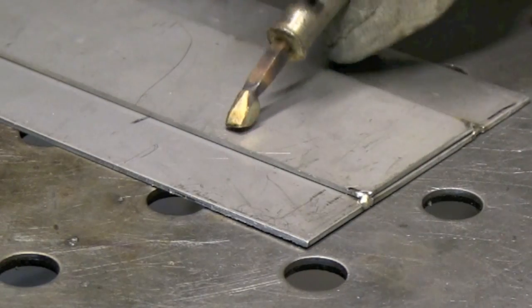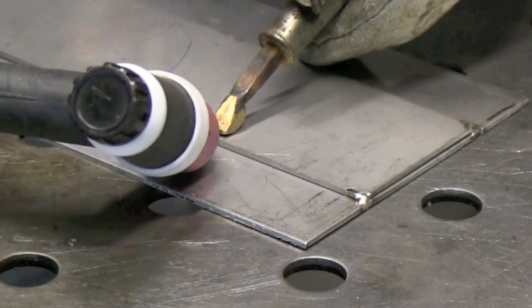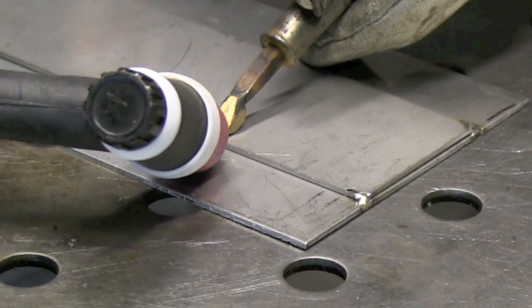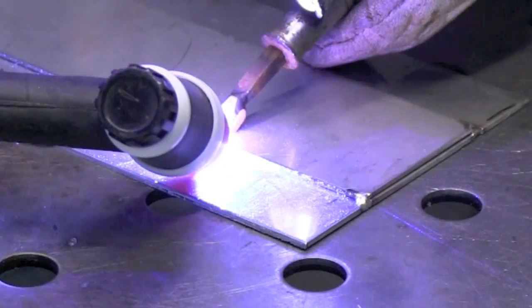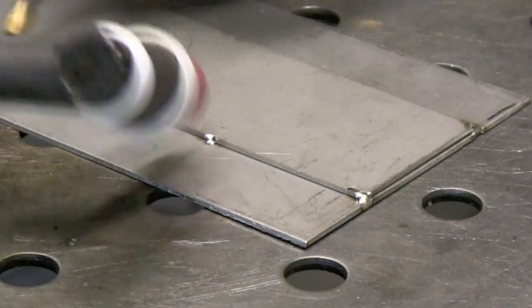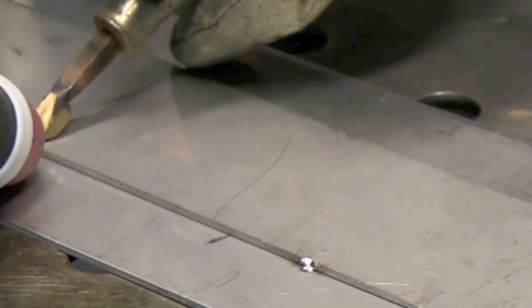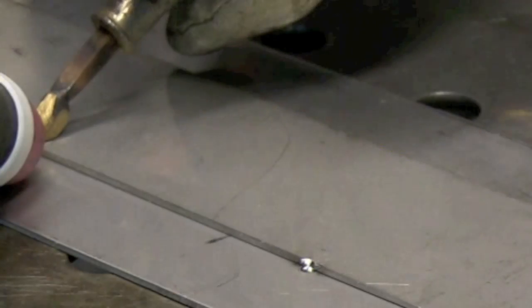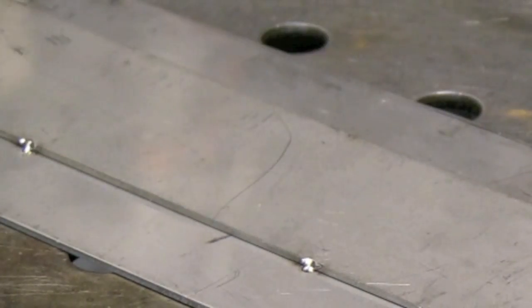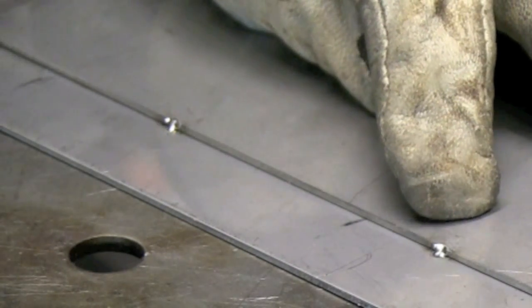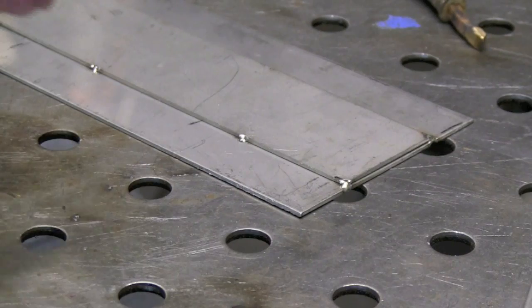Also, you want to put tacks fairly often. Now, this is just a little small piece that I've got on the bench here, so I'm only putting tacks every 2 or 3 inches, but if this was an actual job, I might put a tack every inch, because you don't want that joint opening up on you. Any kind of gap in a thin lap joint like this will just cause problems.